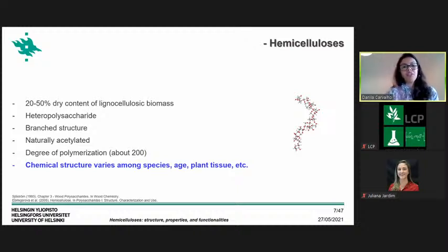Hemicelluloses are a component of lignocellulosic biomasses that can vary between different biomasses from 20 to 50%, and is basically a polysaccharide. Actually, it's a heteropolysaccharide because, unlike cellulose, for example, that's composed of only one monosaccharide, in the hemicellulose it's possible to have different monosaccharides linked to each other to form the molecule. Also, the hemicellulose is branched, which means that there are some side groups in the main structure. It is possible to have some natural acetylation in the hemicellulose, and the degree of polymerization can vary between hemicelluloses, but a number about 200 is something reasonable.